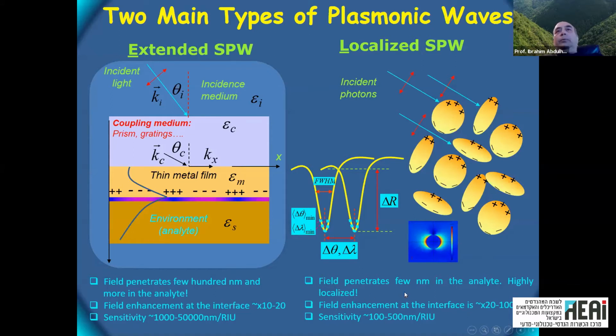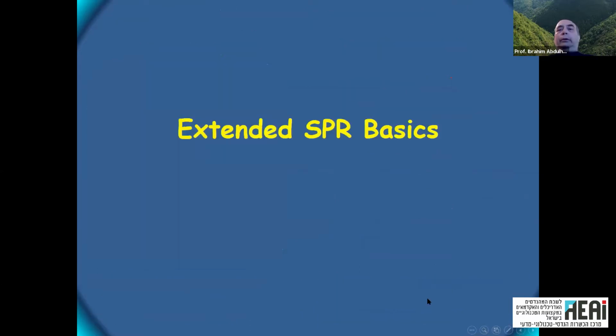And the most important is that the penetration depth here is only at the nanoscale, the very nanoscale, like 20 nanometers, very near the nanoparticle. So it is good actually for small bioentities like molecules, proteins, maybe viruses. For large ones, it is a bit problematic. We need tricks to do that, maybe indirectly. And we will show some cases, for example, using SEF or SERS. Okay, I will go on with the extended SPR first, then we'll switch to the LSPR.